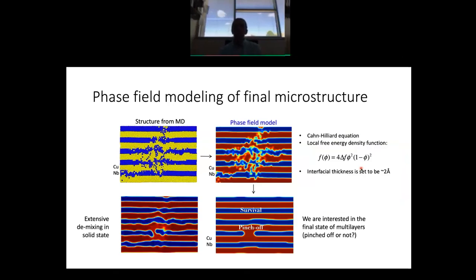Well, to answer that question, we had to go to longer times, right? So we had to use one of the methods that I mentioned to you previously for trying to predict the fate of all the defects that were generated by the radiation. In this particular study, we used the phase field method. So in the phase field method, what we did here is we took this structure that was generated by molecular dynamics, we converted it into a continuum field. So basically, we went from this discrete atomic structure to this more continuous phase field model that uses a continuum order parameter.